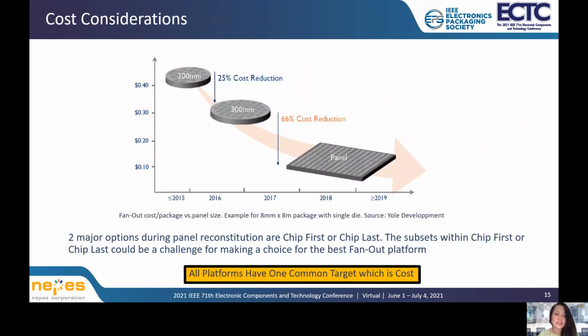From the illustration courtesy of Yole Development, for an 8 mm by 8 mm single die on 200 mm carrier size, a cost reduction of 25% when migrating from 200 mm to 300 mm carrier can be realized. Further cost reduction can be realized when migrating from 300 mm to larger panel sizes.